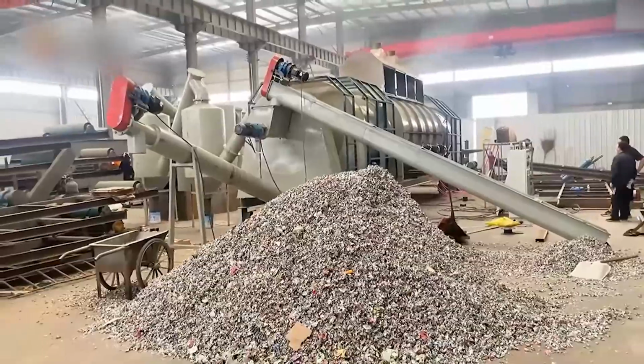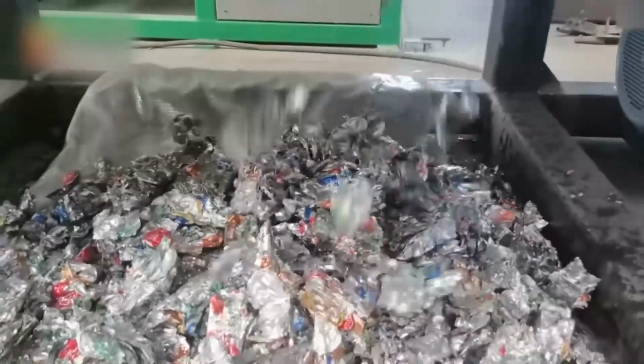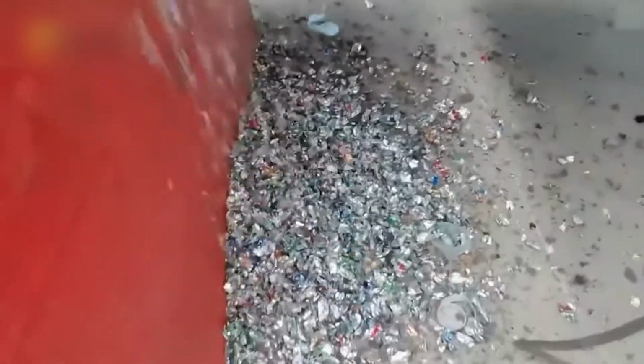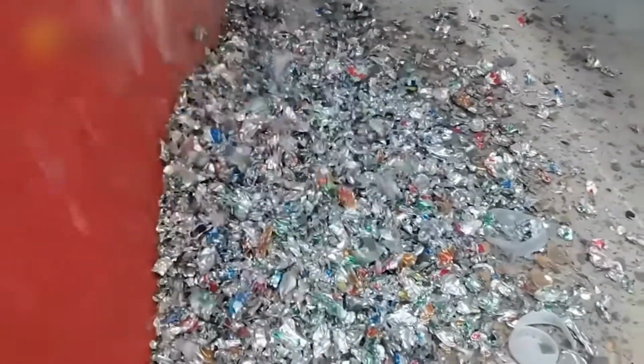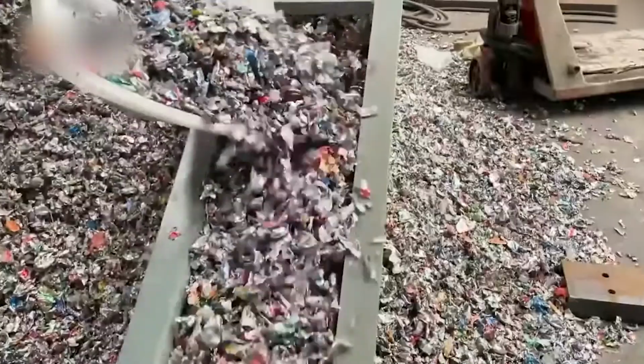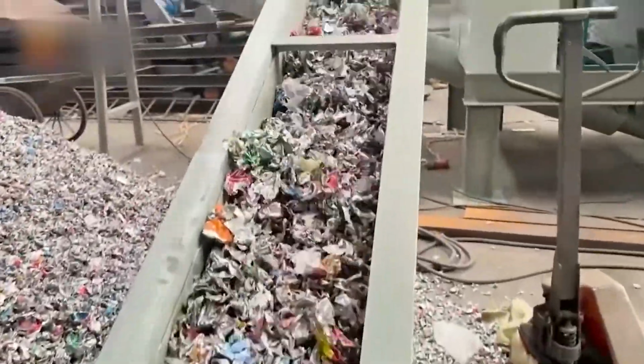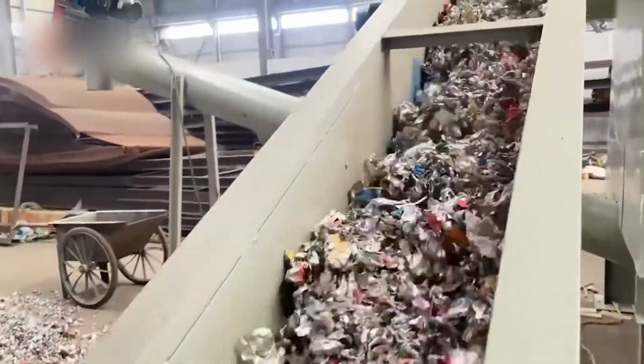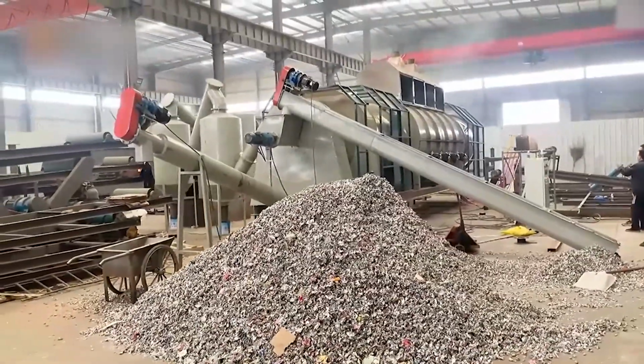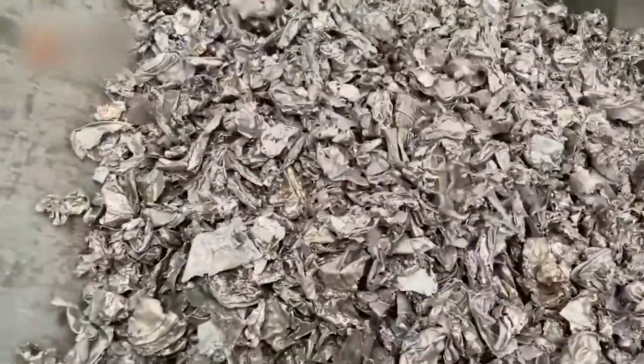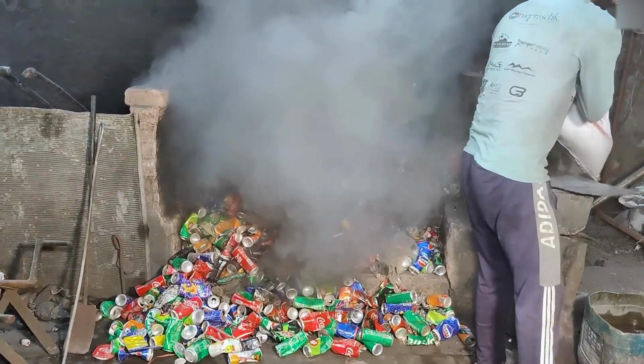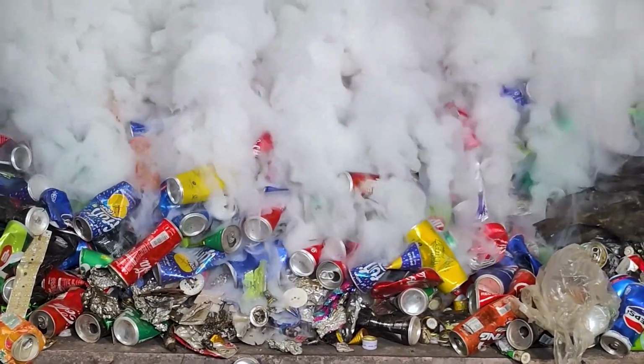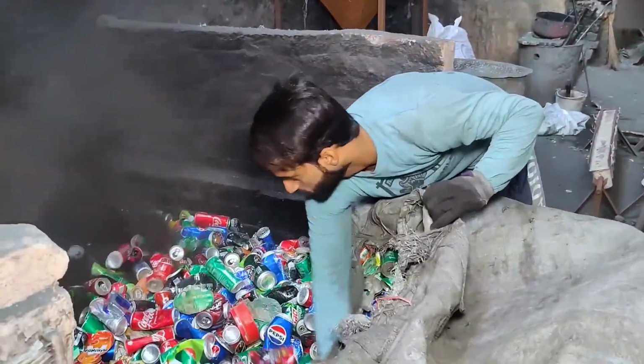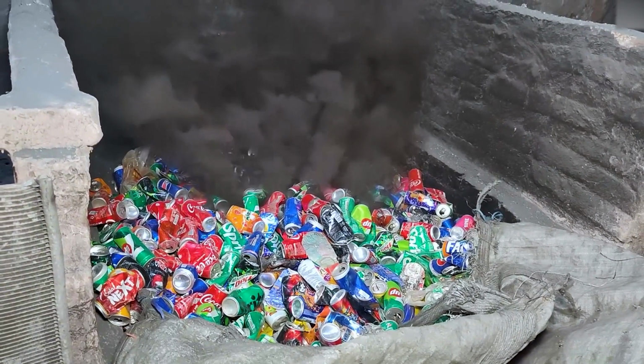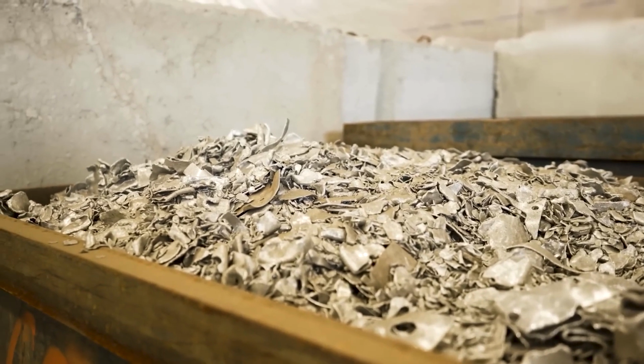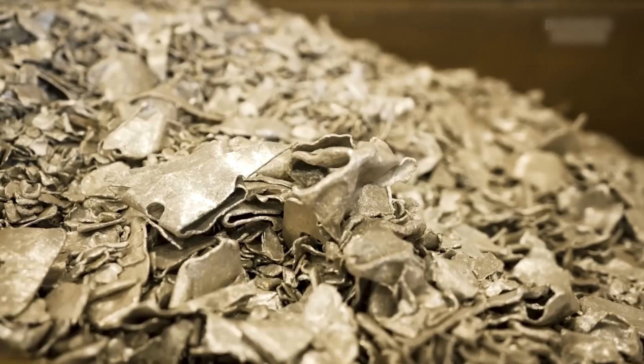Even after being shredded and sorted, the aluminum pieces still have a problem. They're covered in protective lacquers and colorful paint. If these coatings aren't removed, they can contaminate the melted aluminum and ruin the quality of new cans. To fix this, the shredded metal passes through high-temperature furnaces that heat up to over 700 degrees Celsius. That's hot enough to instantly burn away the paint and lacquer, leaving behind clean, bare metal. As the aluminum shreds move through the furnace, powerful airflows carry away the vaporized coatings so they can't settle back onto the metal. This step is crucial because even a small amount of leftover residue could cause defects in the final product. By the time the aluminum exits the furnace, it's spotless and ready for the next stage, melting it down to make new cans.